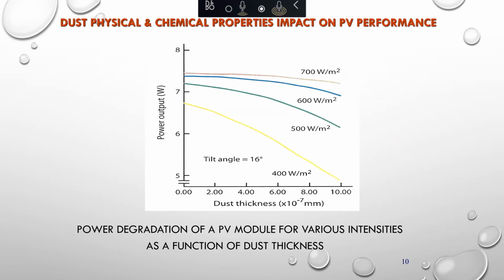So the problem is the finer dust. This one was done in Kenya, and they looked at different intensities here, as you see, 700, 600, 500. With higher intensity, they found that the reduction in output versus the thickness of the dust was minimum. But as you see here, when you go down to 400 watts per square meter, the loss was near 25% with lower intensities.